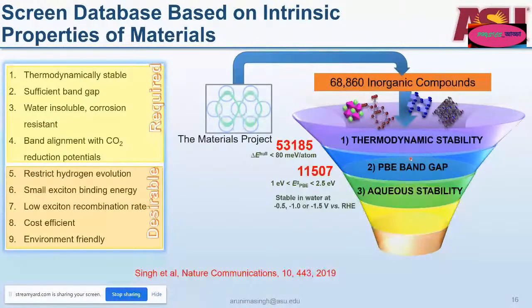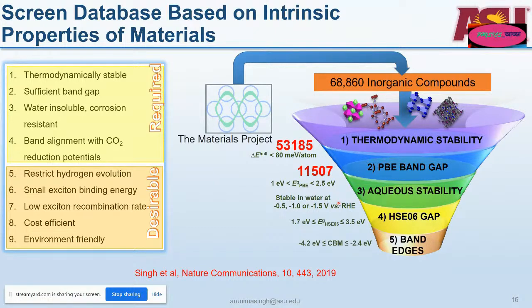The next bit was looking at how stable these materials are in water. Looking at the stability is critical. These reactions happen at reducing conditions, and reducing conditions can be highly corrosive for materials. Most materials hydrolyze or convert to their metallic forms under these conditions. But there was no way to assess the aqueous stability of metastable materials using the existing routines in the Materials Project. And then we decided to look at the band edges, which is the band alignment with CO2 reduction potential,